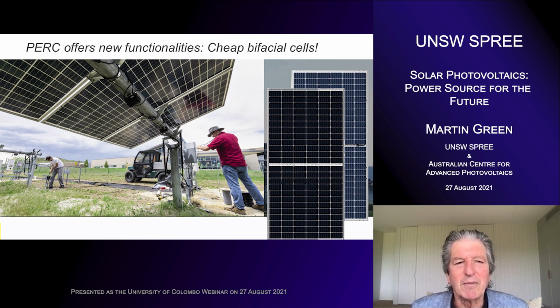So by having a solar panel bifacial, and the photo at the right just shows a module from the front and the back, so they look pretty much the same from both directions. By having bifacial, you can boost the output by somewhere between about 5% if you don't do too much to increase that rear light falling on the module, to 20% if you make a bit of an effort. So a 5 to 20% boost in output, essentially for very little extra cost. So that's become quite popular now. And you can see these modules here, they're mounted on what is a sun tracker.